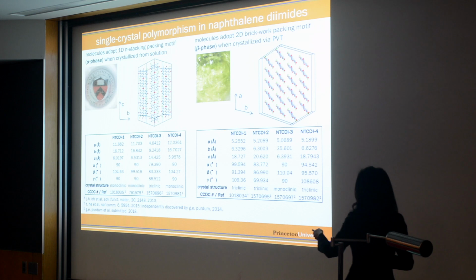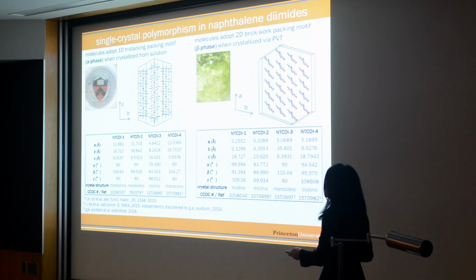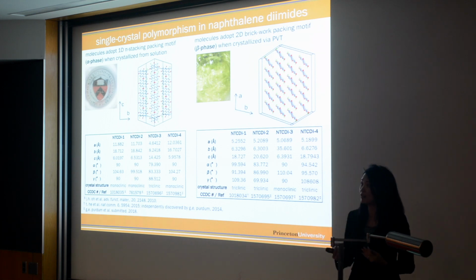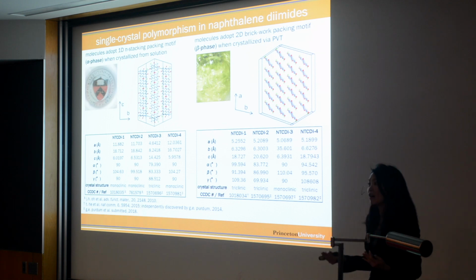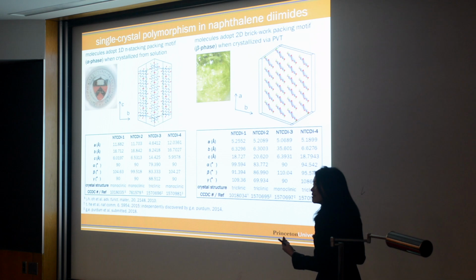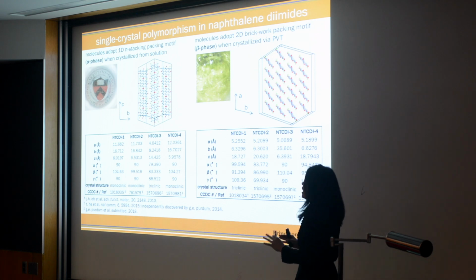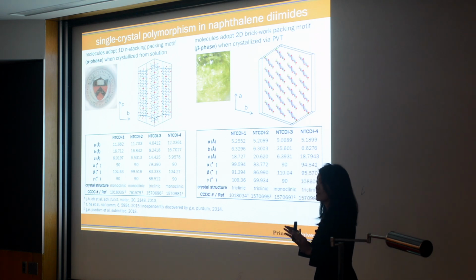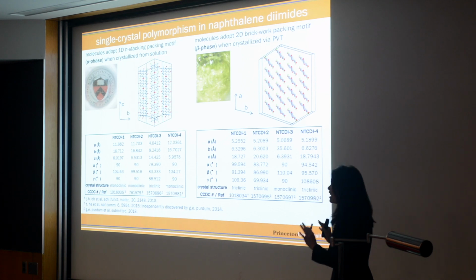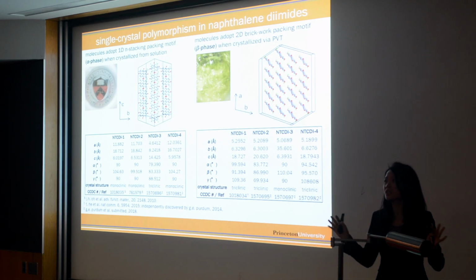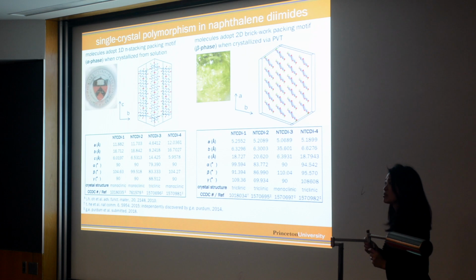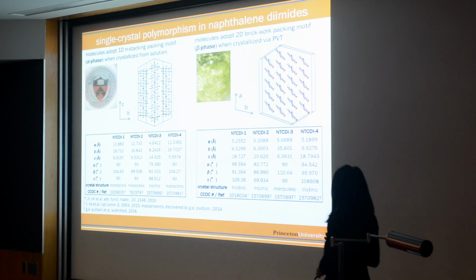We can access the alpha phase for all compounds. We can access the beta phase for all compounds. And when they're in their alpha phase, they look more or less the same. When they're in the beta phase, they look more or less the same. So these are quasi-equilibrium conditions that we're growing these single crystals. Okay? So it turns out under quasi-equilibrium conditions, you can access these. The subtle chemistry does not appear to matter.